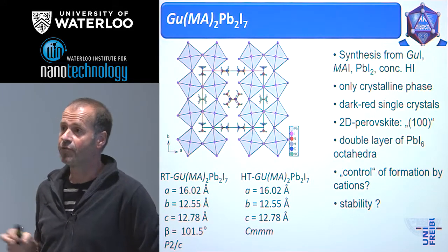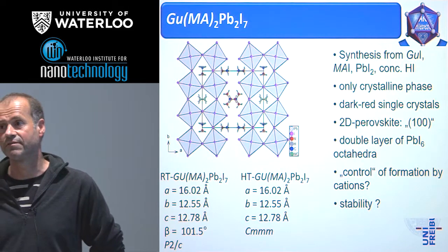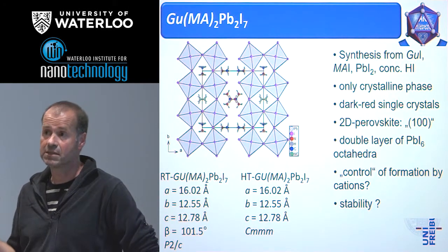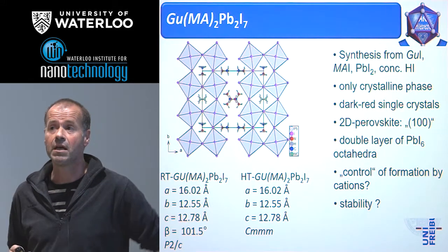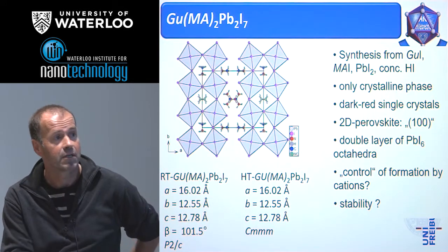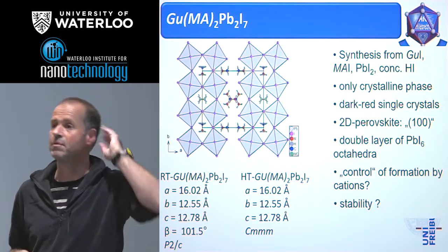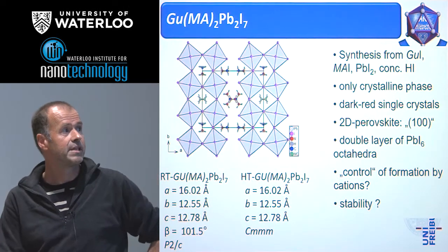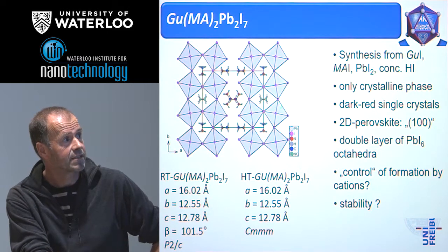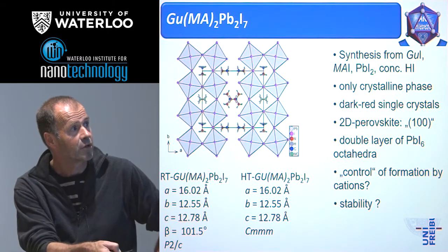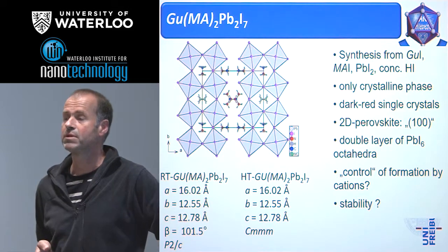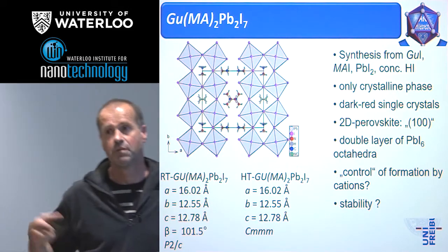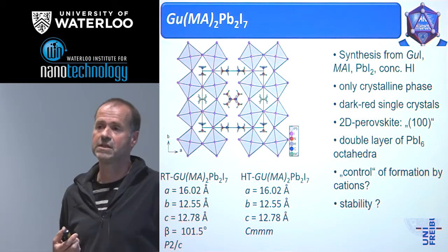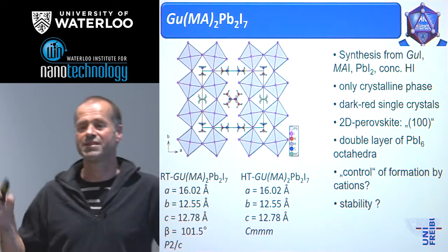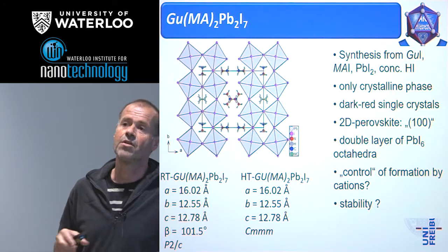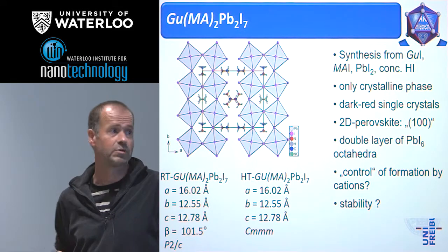The best band gap for a solar cell is about 1.75 eV. That depends on the maximum efficiency of the solar cell, and we see that with the dark red single crystals we are a little bit above. That means the band gap is a little bit larger. You see, 2 of these layers are combined to a double layer and the octahedra are rotated. This is important because the optical properties, and following that also the other physical properties, demand this type of distortion, because that's good for an efficient absorption process.